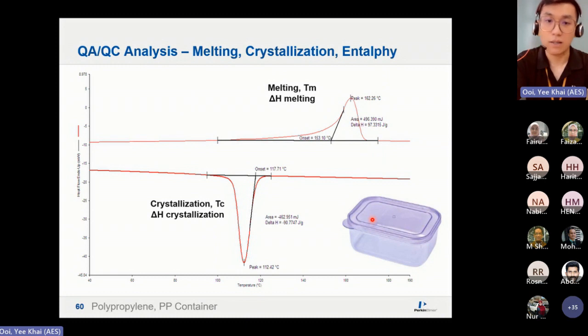So your wax, okay, why do you need to prevent wax from forming inside the crude oil during transport? Because wax by itself is crystals, meaning it's a crystalline form of the crude oil. That is the wax that you see inside the transfer line. So this is why PE and PP are always highly crystalline materials, and you will see melting and also crystallization. When you do heating, you get melting. When you do cooling, you get recrystallization of your material. No TG, right? Because this is fully crystalline material.